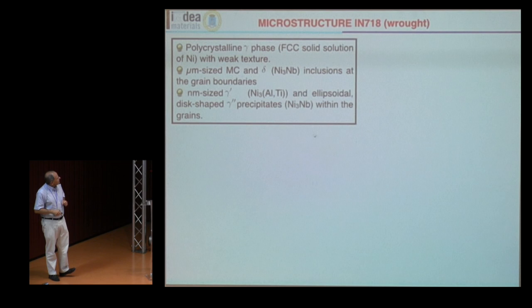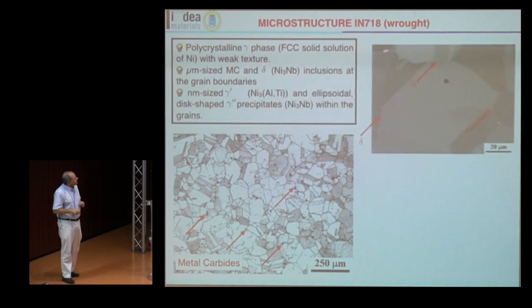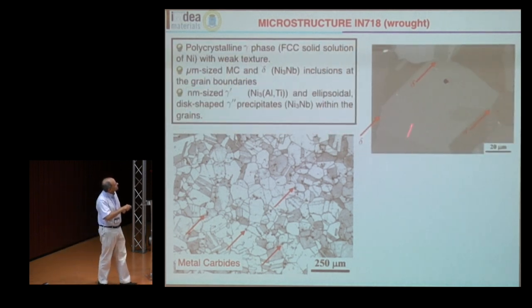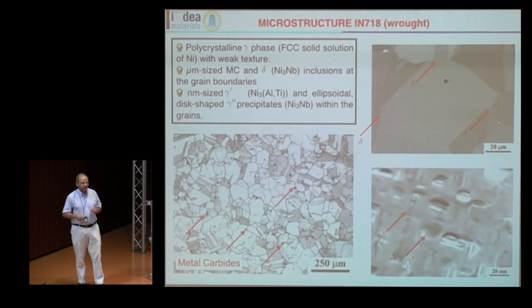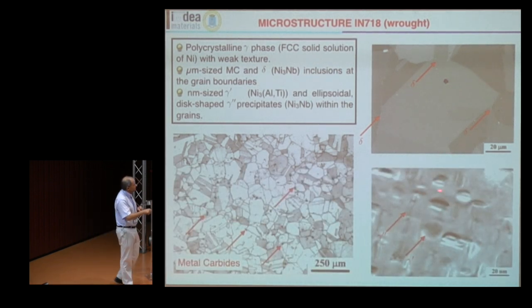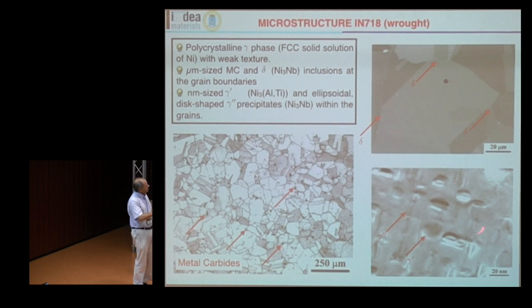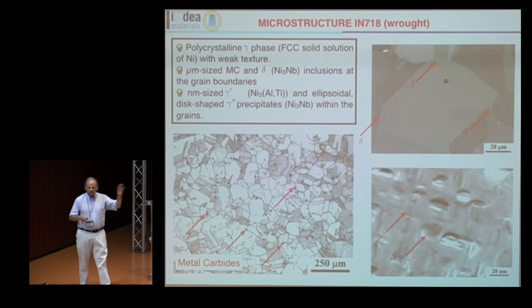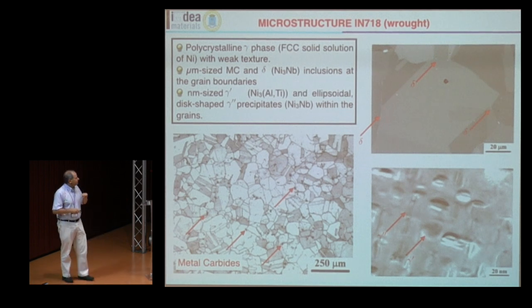The material is a nickel-based superalloy. This is the typical structure: you can see the grains, some metal carbides. At higher magnification it's an FCC solid solution of nickel with delta phase at the grain boundaries. At even higher magnification, you can see a huge volume fraction of gamma prime and gamma double prime precipitates — very important for strength. The length scale matters here: the precipitate size is about 20 nanometers and the spacing between precipitates is 20–30 nanometers. This will be important later.